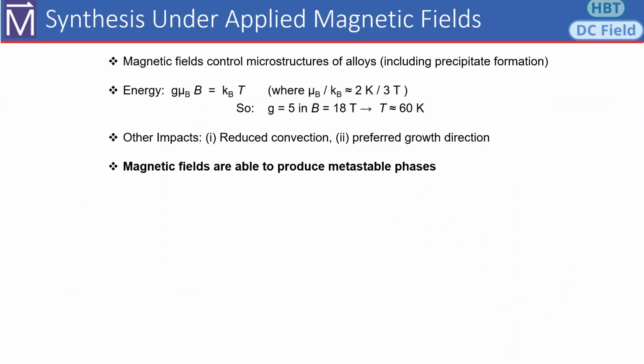To begin with, it's already very well established, to the point where it's even used in the steel industry, that magnetic fields control the microstructures of alloys. So in that sense, this is already well established, but for our sorts of work, I think it's fair to expect that an applied field would also have an impact on precipitate formation. And I also just want to say that in these strongly correlated electron systems, we know that you grow it a little bit different way, you look at it the wrong way, and its behavior changes, right? This means that there's very fine tuning that wouldn't necessarily require large energy scales. So for example, for uranium tellurium-2, I think there are some interesting questions to be asked here.